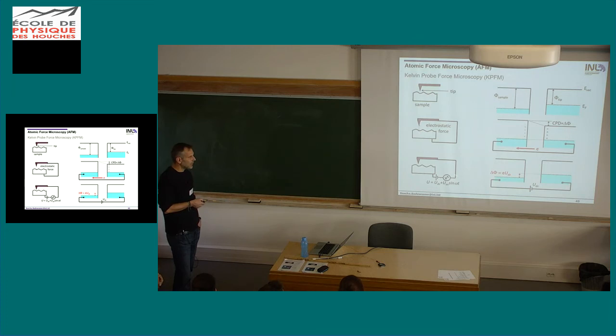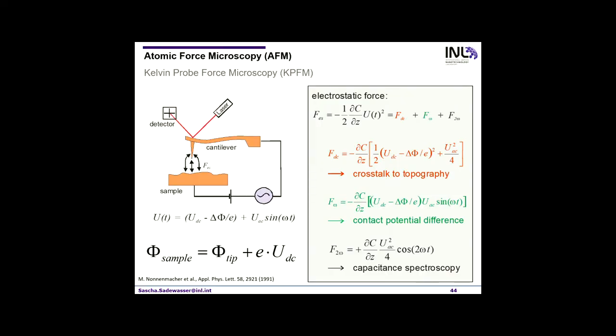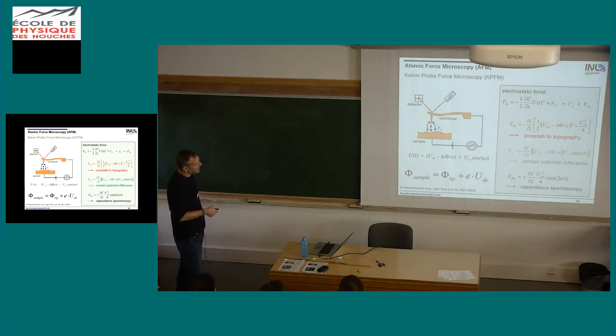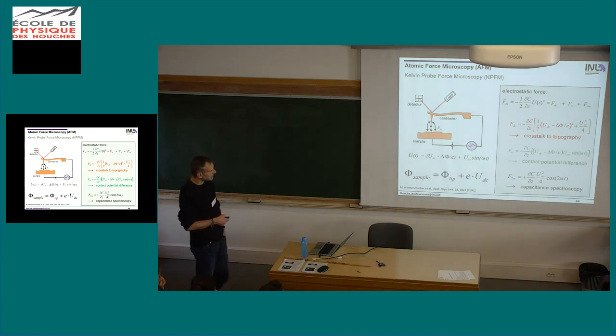And in order to do this in our microscope, we also need to apply an AC bias, and this is explained here. So our system in the end looks like this. We have a cantilever, the tip and the sample. We have a DC bias, the AC bias, and then the total voltage between the tip and the sample is the DC bias that we apply minus the contact potential difference plus the AC bias.